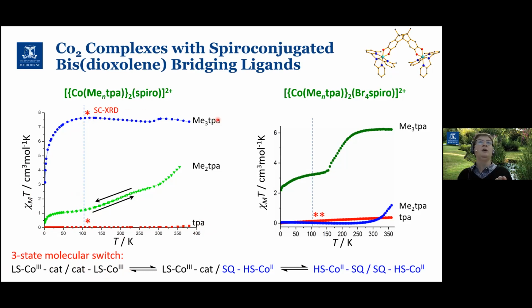On the other hand, when we go to the trimethyl TPA, again, like the monomer, both the crystallography at 100 Kelvin and the variable temperature magnetic susceptibility are telling us that that dimer is pretty much stuck in the high spin cobalt-2 semiquinone form at both halves of the dimer. So the sweet spot in this case, again, is the dimethyl TPA. It's with the dimethyl TPA that we actually see two steps in our Chi-T profile, and that's the closest thing that we have to a two-step VT transition.